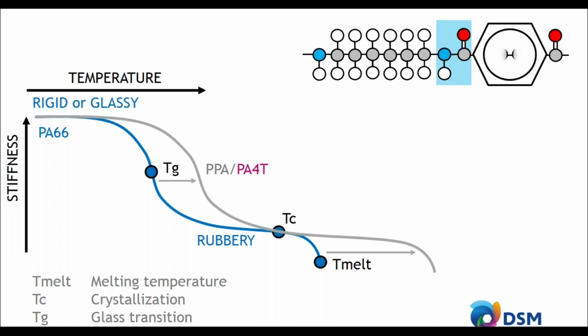But what if you would introduce a ring structure in this polymer? A lot is happening then. You can increase the glass transition temperature from 70 degrees up to 150 or 160 degrees C. These types of polymers are called PPA, and DSM has a PPA based on the PA4T technology, where the T represents that ring structure. So you increase the operating temperature already.